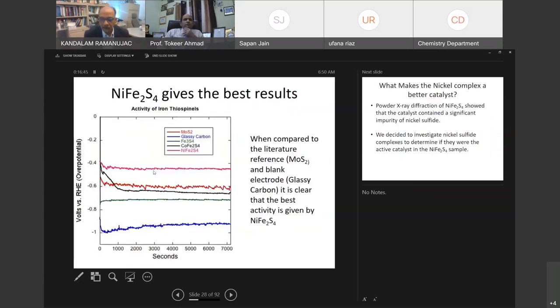To make the long story short, this gives you a summary of the performance of all these spinels. Our reference material here has been molybdenum disulfide, which has been shown in the literature as an attractive alternative to platinum. Our idea is to make materials that are much better than molybdenum sulfide. As you can see from this graph, clearly NiFe2S4 has outperformed the molybdenum sulfide. The molybdenum sulfide has an overpotential of approximately 0.6. However, we were able to reduce that overpotential by 0.2 units, which is significant.